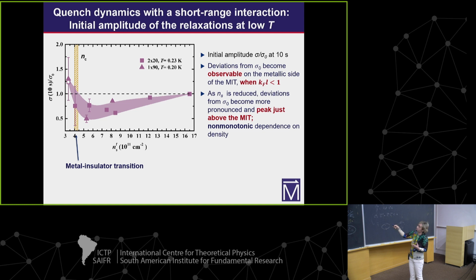We see that as we reduce the density, this grows, and it's non-monotonic. It's really most pronounced just above the metal insulator transition. So this is another property of all these systems that reflects the presence of an underlying metal insulator transition.